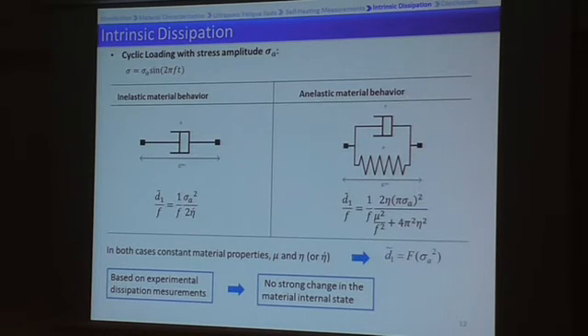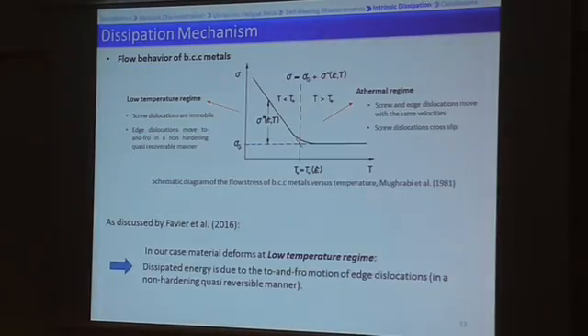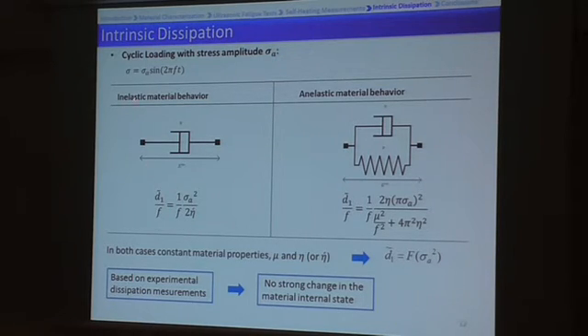So if we consider the cyclic loading with the stress amplitude of sigma A, considering the inelastic material behavior using the Kelvin-Voigt element, it's well defined in the literature that we can measure the dissipated energy per cycle by these two relationships in each case. Here, mu and eta are material parameters representing the elastic and viscous moduli of the material. We can see that in both cases, if we assume that eta and mu are constant, D1 will be a quadratic function of sigma A, which is inconsistent with the results we obtained in our experimental researches.